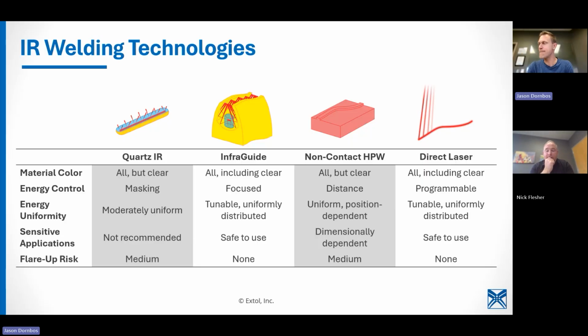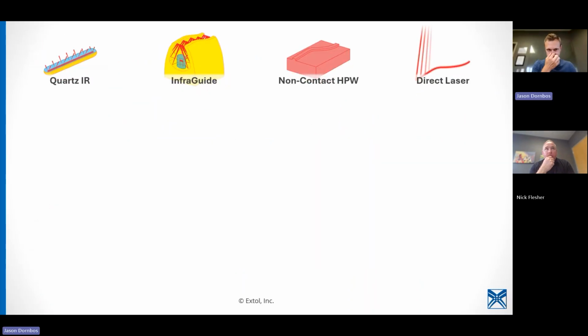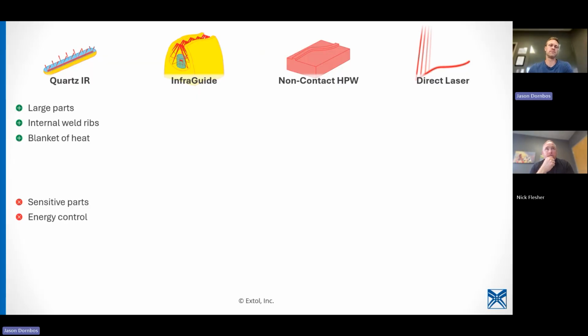Direct laser. How big of parts can you do? Yeah, so I think go to the next slide there, Jason. What I would say is for Quartz IR, larger parts are more suitable. We find that we shift to quartz for emitters when the parts are really large, or the weld ribs are internal. With InfraGuide, since we're using a focus tool, you can't really design it if ribs are really close together. It's a little bit better to mask the energy and use the quartz.